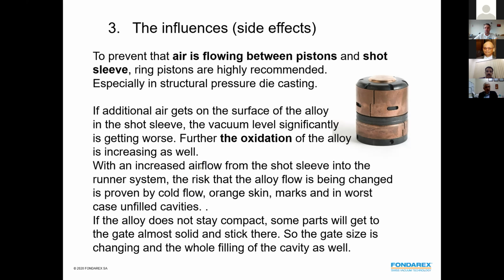The problem is the airflow in the runner. It has the tendency basically to suck metal. It doesn't really suck metal, but let's say the velocity and the volume of air is higher. Therefore, it has a higher influence on the surface of the metal, which goes towards the cavity. And the die caster was saying, oh, the vacuum was sucking the metal. If we have an absolutely tight system, it's impossible to suck metal.